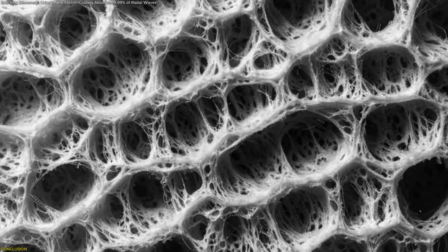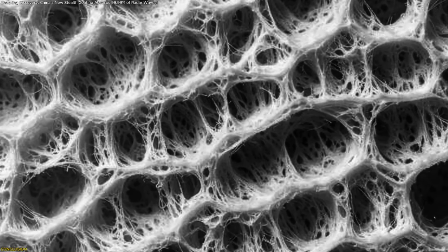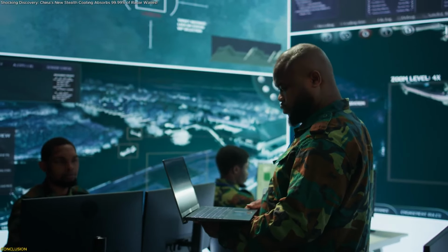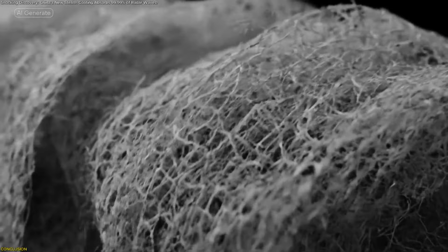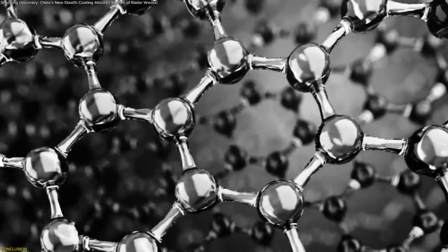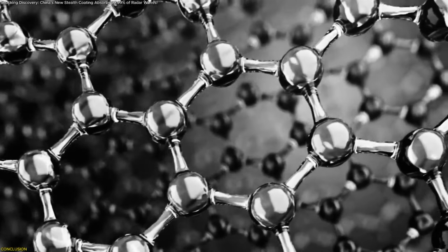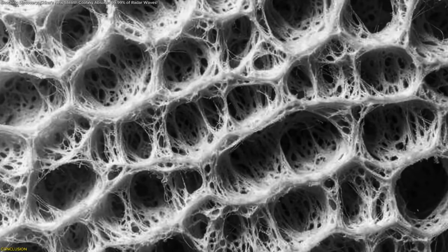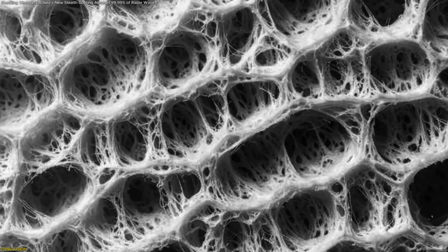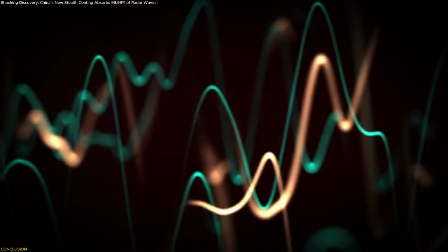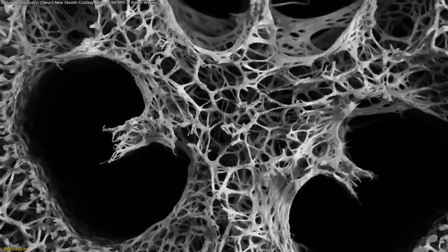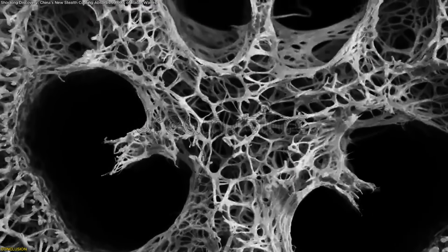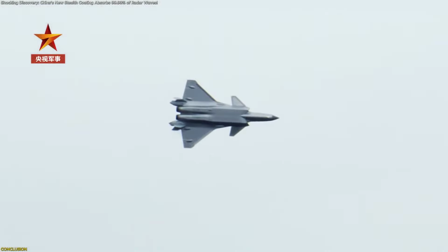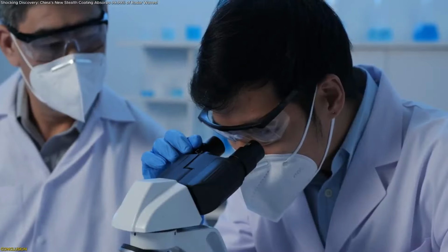China's loofah-derived NCO2 composite represents an unconventional but highly effective approach to reducing electromagnetic visibility. By leveraging the natural 3D network of the loofah plant, carbonizing it into a conductive scaffold, and enhancing it with magnetic nickel cobalt oxide nanoparticles, researchers achieved a material capable of absorbing over 99.99% of Ku-band waves. Its thickness of only 4 millimeters and ability to maintain performance even with overhead signals make it an important development in advanced materials research.